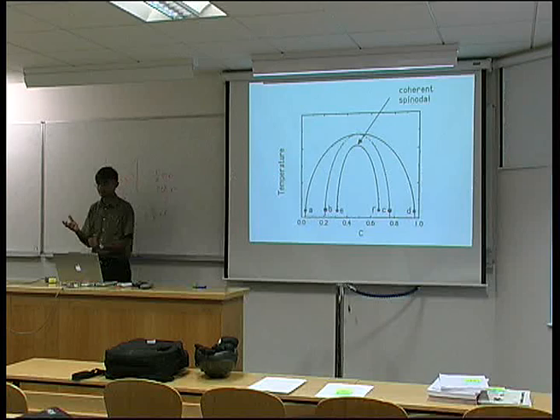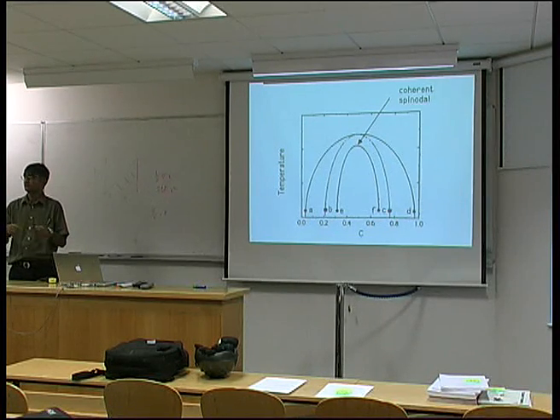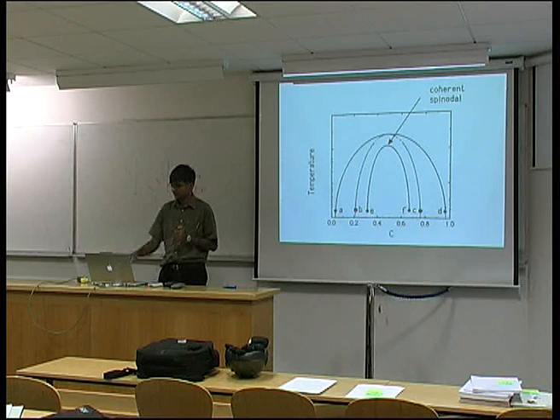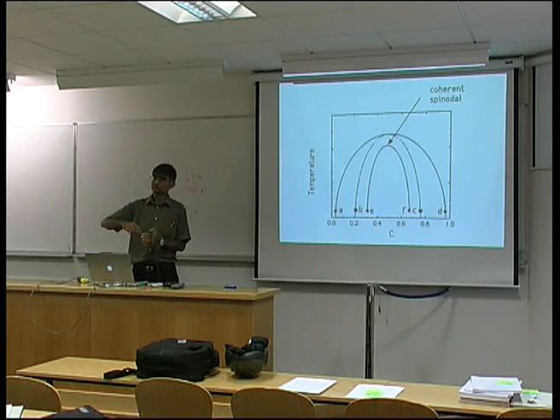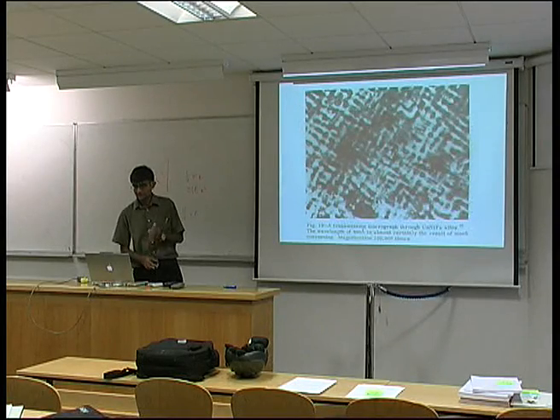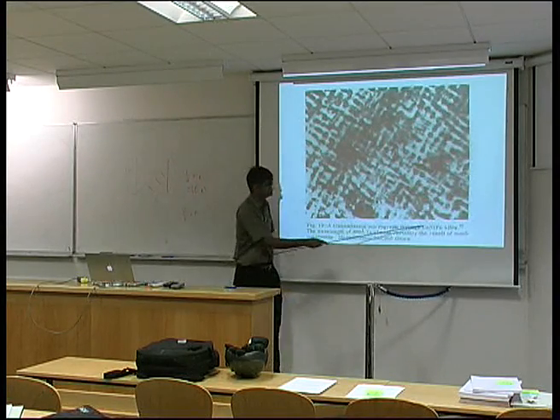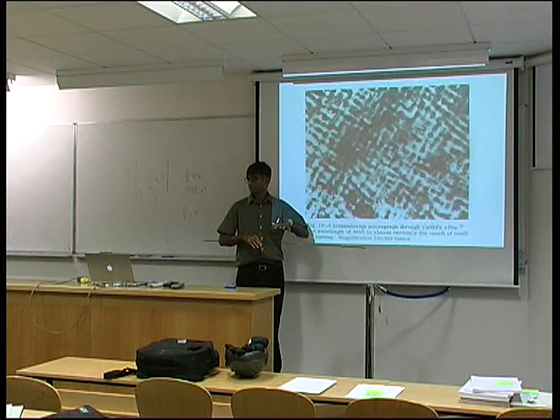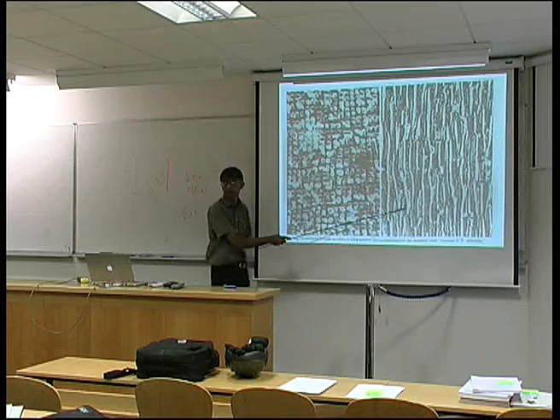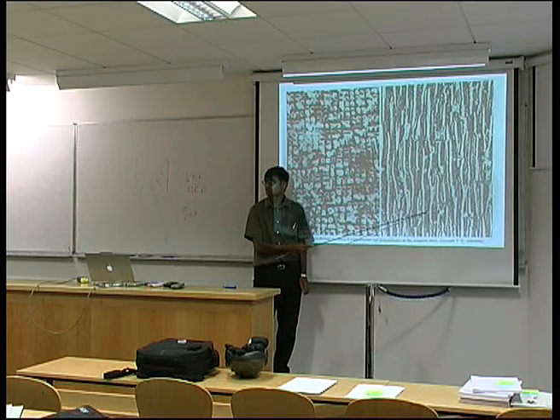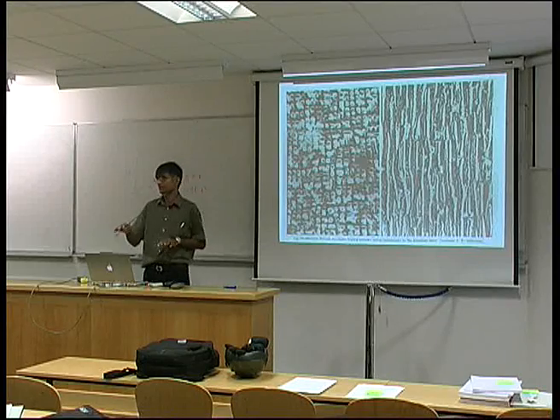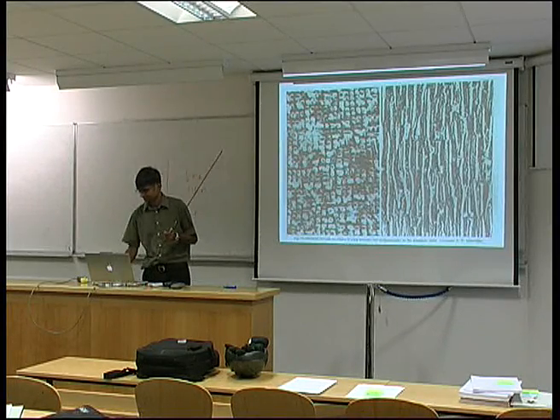Crystals are not isotropic - their properties vary with direction, and one of the properties which varies with direction is the modulus. If the modulus varies, then it might be easier to develop a composition wave along one direction than another. This is exactly what you see: in a copper-nickel-iron alloy which is slightly anisotropic, the spinodal is fairly isotropic. But in a system where the modulus along one direction is very different - very small compared with another direction - the decomposition process becomes extremely anisotropic.